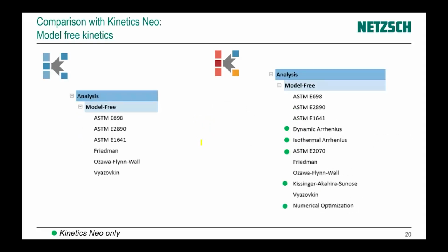For model-free kinetics, Lite has 2 groups for single-point and for multi-point kinetics. And Kinetics Neo has additionally single-point dynamic Arrhenius, isothermal Arrhenius, and multi-point ASTM E2070. Additionally there are Kissinger, Akahira-Sunose, and now our NETZSCH numeric optimization, where we make additional optimization of a Friedman solution in order to have it better.